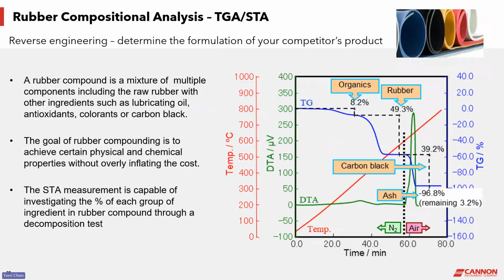Here is another example of using TGA-STA technique to do reverse engineering study and find out the formulation of a competitor's product. Rubber compounds are mixtures of multiple components, including natural and synthetic rubbers, some small molecule ingredients such as lubricating oils, and other ingredients such as cross-linking agent, colorant, inorganic fillers, or carbon black. The goal of doing rubber compounding is for the purpose of achieving certain mechanical and physical properties without overinflating the cost. A TGA-STA analysis can help quantifying the weight percentage of each ingredient group in rubber compound.